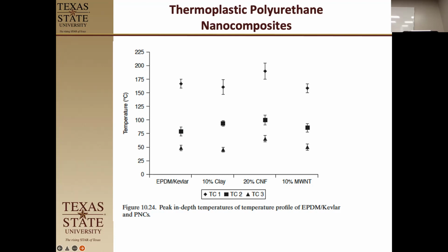When we use carbon nanofibers for thermal conductivity, it actually helps draw heat into the system faster, which is why maybe it doesn't perform as well, because your pyrolysis zone is so far in that you're outgassing, you can't perform foam action. And then we saw the same thing with the carbon fibers and with the multi-wall carbon nanotubes. It's a little bit higher, but not as high as the carbon nanofibers. Carbon nanofibers are longer, have a longer persistence length, and therefore heat can travel faster through the system. And they weren't looking for heat transfer. Notice also that the carbon nanofibers were 20%. So it was the highest loading, and it's probably the highest thermal conductivity filler they used. So that accounts for that shift in the temperature range between those systems.